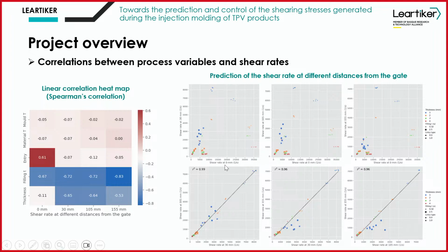So if we analyze the relation between the location 0, which is the gate, and the other positions, it can be seen that there is no relation between them. But if we exclude the 0 position, the position in the gate, then it was interesting to observe that we are able to predict what's happening in the other positions. That's it. If we know the shear rate at 30, there is a linear correlation with the shear rate at 105, and the same happens with the other ones.